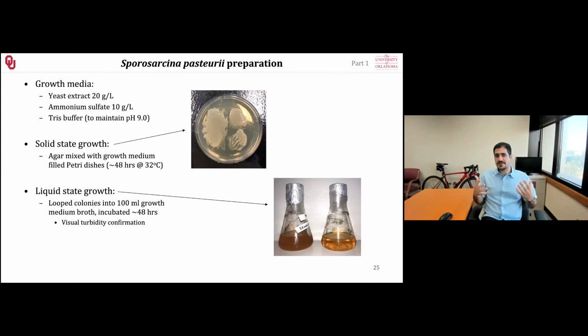Specifically, for the lab experiment, we are using a type of microbe called Sporosarcina pasteurii. These microbes are known to produce large calcite crystals, and they're very active in decomposing the material to produce calcite compared to the other communities in the subsurface. But we are just using these because we are using a lab measurement here. In the field, we don't really need this type of microbe. All other types of microbes capable of precipitating calcite are going to work, which I'm going to talk about.